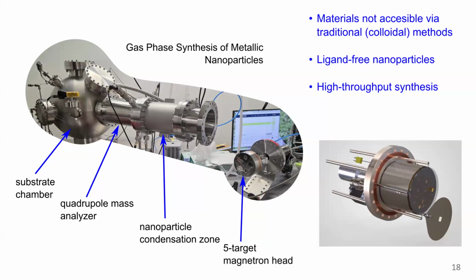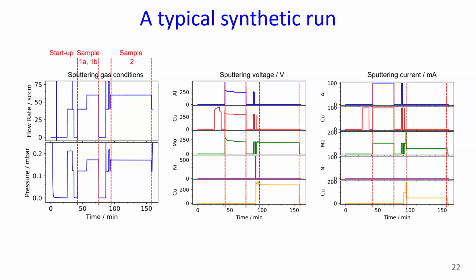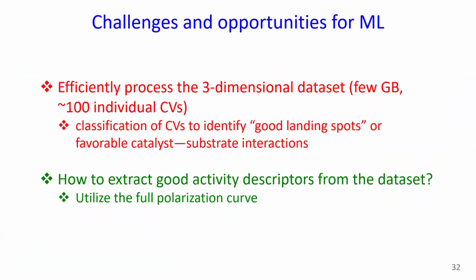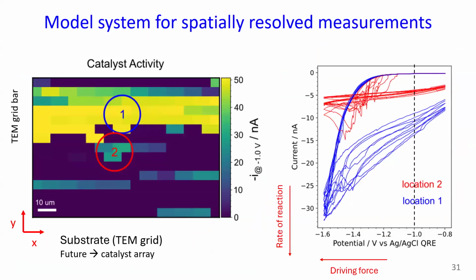I might have missed this from the CV plot, but how do the durabilities of these high-entropy catalysts compare to the copper nanoparticles? Yeah, exactly. We haven't begun to address durability yet. That's essentially a secondary question. First, we want to identify an active catalyst, then we can look at durability, because in order to do durability, you just need to run it for a long time. People come up with all kinds of accelerated durability tests, but the real measure of durability is how long it actually runs. If you want to measure legit durability, you need to do long-term experiments, and then it's not going to be high throughput. They're kind of mutually exclusive. So the strategy is to first identify promising materials and then look at durability.